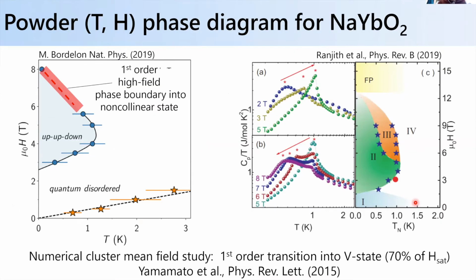Good. And so this is kind of going back to the question that I was just talking about. With the powder data, which is the best we can do with sodium ytterbium O2 right now, we can just plot an effective powder average phase diagram where you have the field versus temperature. And the phase boundary here, measured down to 50 millikelvin at this point, shows that you have this transition, which is reasonably sharp, from what seems to be a quantum disordered state into this fluctuation-driven up-up-down state.